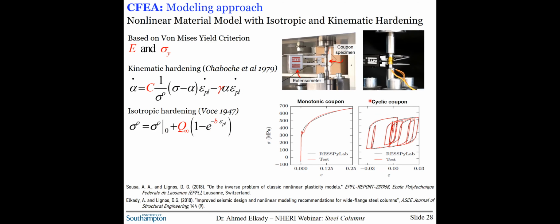Probably the most important part in the model definition is the material model. And here we used the nonlinear model with isotropic and kinematic hardening that you typically use if you are using any finite element software like Abaqus or ANSYS or such. To properly obtain the hardening material parameters of this model, we had to conduct carefully executed monotonic and cyclic coupon tests for the calibration.